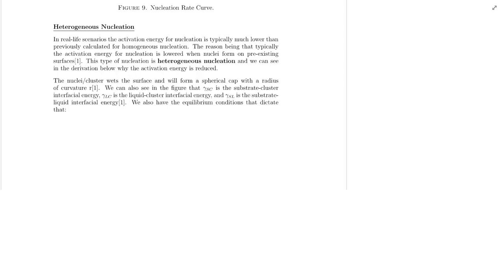We talked last time about homogeneous nucleation, and the big kind of takeaway from that lecture was a couple of things. So we found that this delta G R had these two terms, which one was negative, so one was four-thirds pi R cubed delta G V, plus this interfacial term, four pi R squared times your gamma SL.